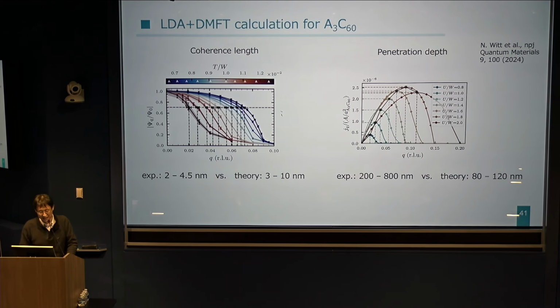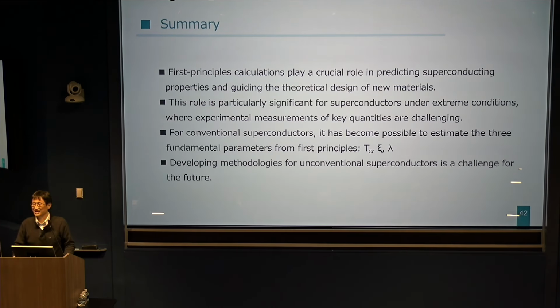Recently we performed a calculation to estimate coherence length and penetration depth, and these are the results. For Xi, I would say that the agreement is good. For penetration depth, given that experimental determination is a bit difficult, I would say that the agreement is not so bad. But anyway, the calculation of Xi and lambda in unconventional superconductors is an interesting future problem.